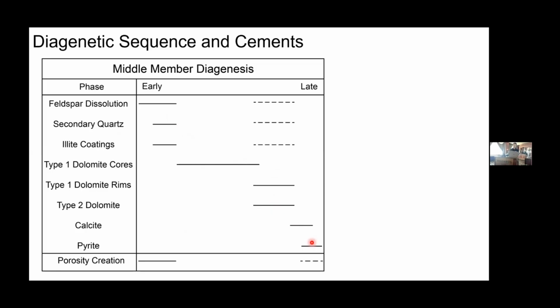I'm not going to get into a lot of discussion about porosity creation today, again, due to time constraints, but the largest amount of porosity creation that we observed is related to that early feldspar dissolution, with much more minor stages later on in the diagenetic history associated with dissolution of some of those carbonate cements.